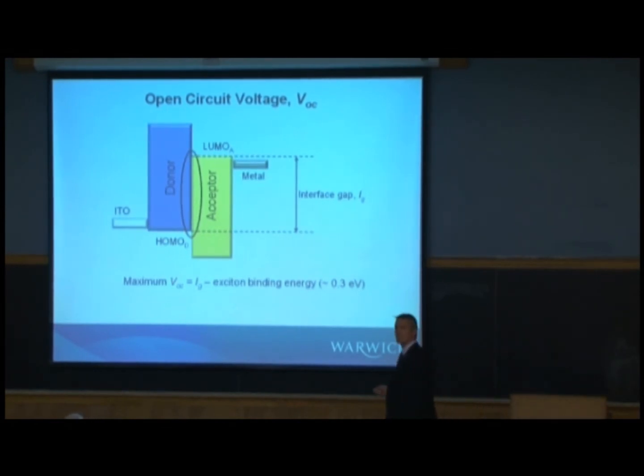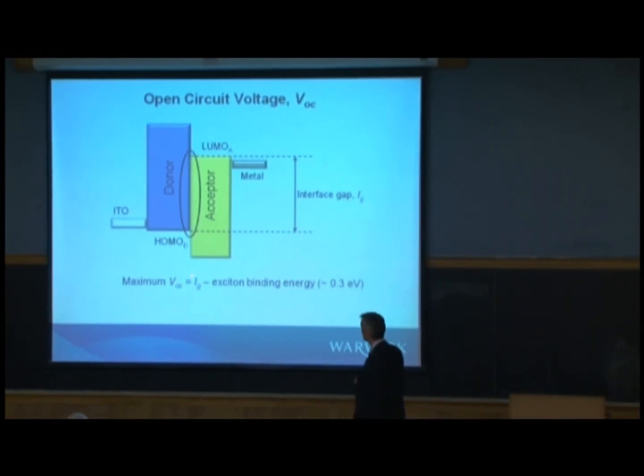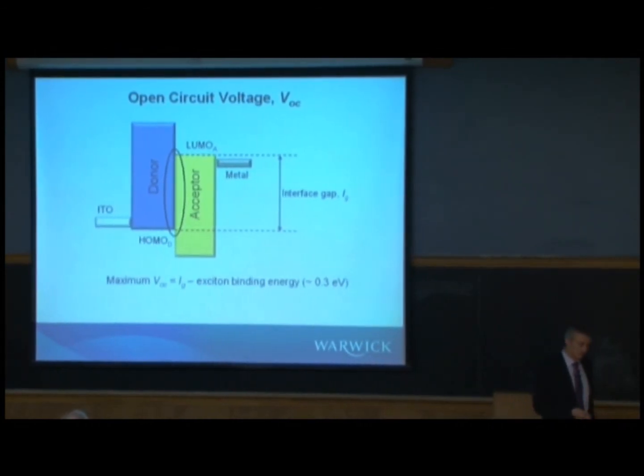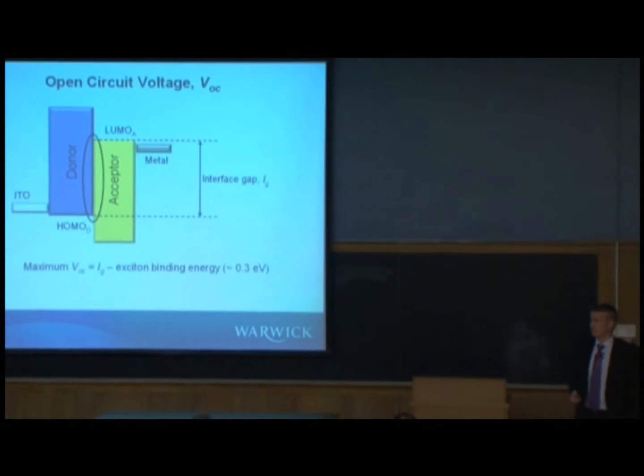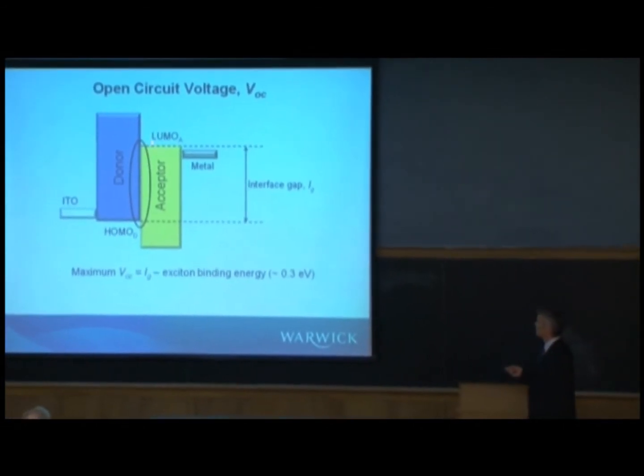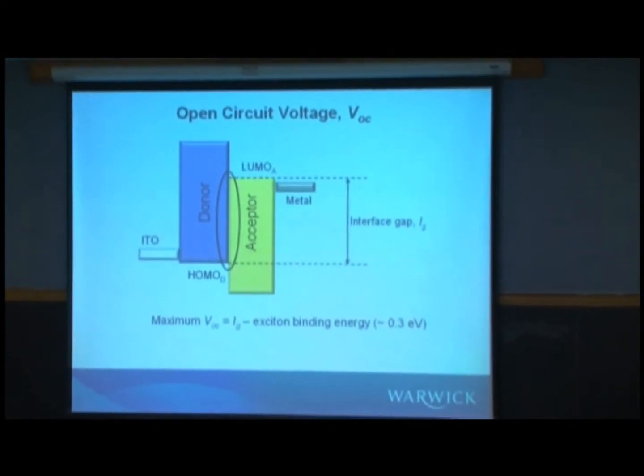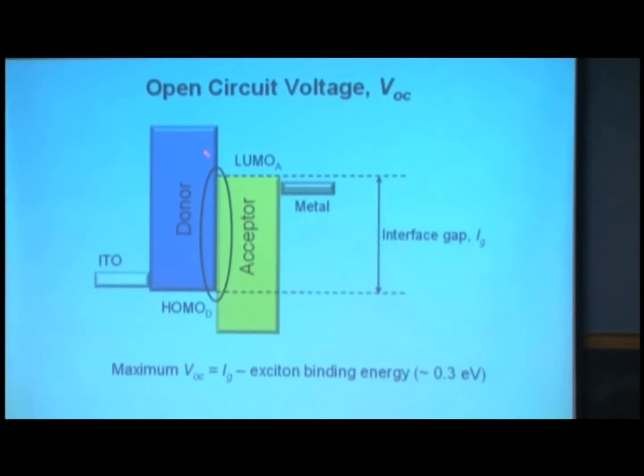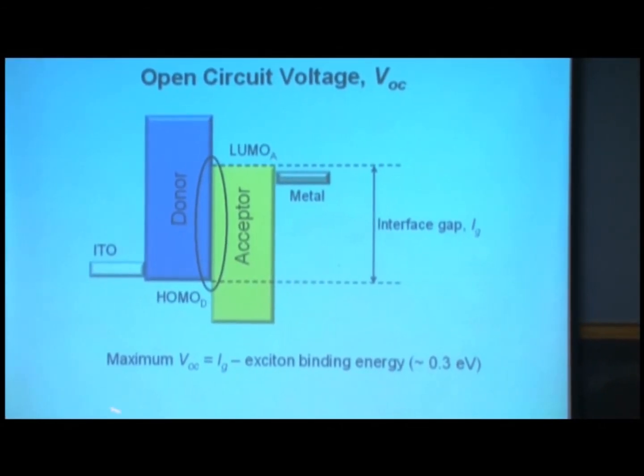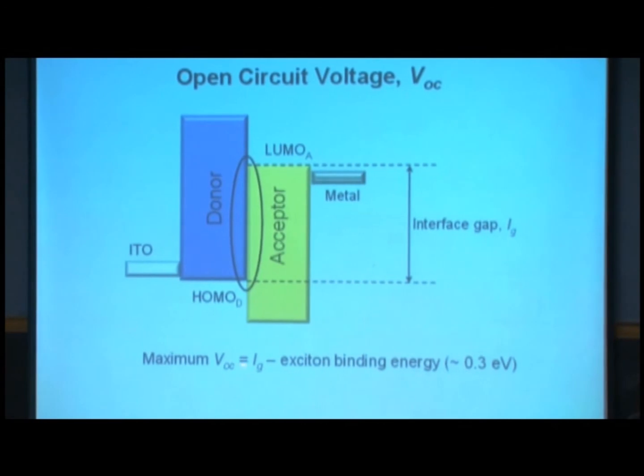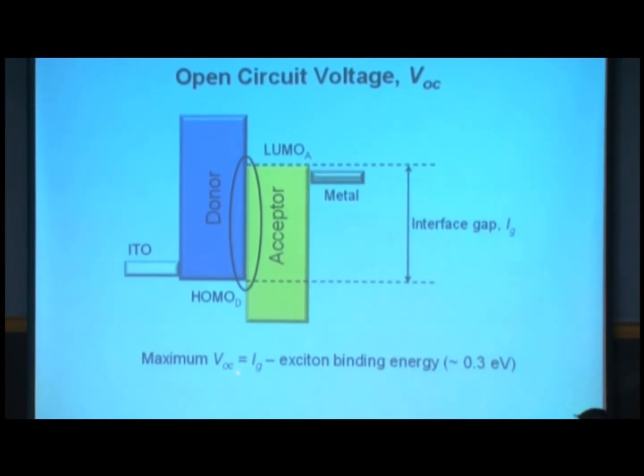The maximum voltage you can extract is basically the interface gap energy minus some loss, which is essentially related to the binding energy of the excitons. In other words, the energy needed to dissociate the excitons at these interfaces, so the offsets between these energy levels. So in order to maximize your voltage, you need to maximize your interface gap, remembering that these offsets have to be high enough to dissociate the excitons. So it's a compromise between those different energetics.